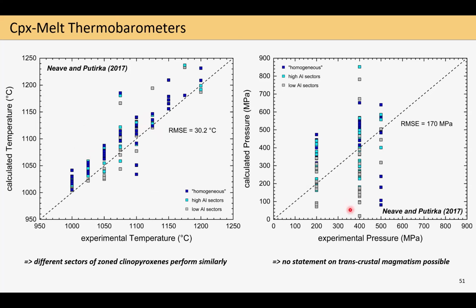But if you have a look now at pressure, the story looks quite different. So for example, when we have a look at my 400 megapascal experimental clinopyroxenes, we see that the calculated pressures predicted by this barometer more or less range from 900 to almost 0 megapascal, meaning they cover the entire crustal column. And this then means for me that currently we cannot use such thermobarometers or barometers based on CPX or CPX-melt to make any reliable statements regarding a transcrustal magmatic system. So potentially, I recommend you keep this in mind when you next apply such barometers to your natural samples.